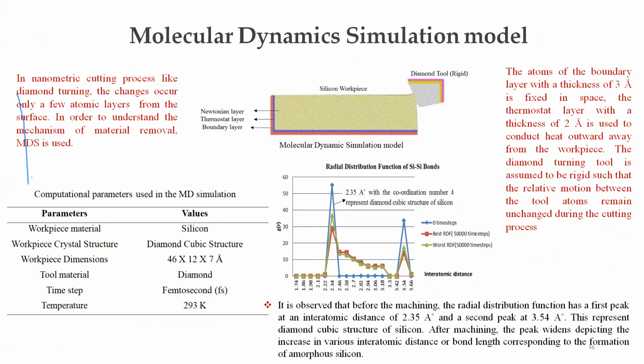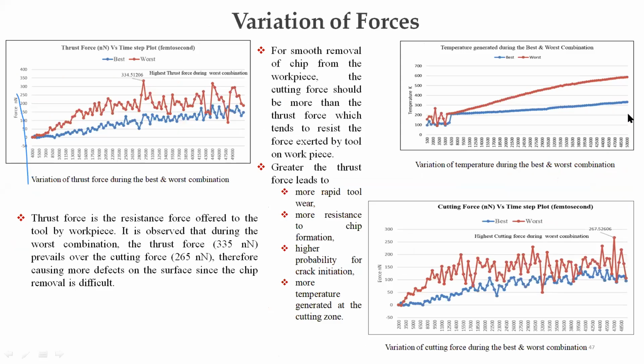Now, since I'm talking about nanometric cutting, the things are not usually visible to us. So in order to analyze the process, we are into molecular dynamics simulation modeling. We use this model to analyze the nanometric cutting, the changes occurring in the material only a few atomic levels from the surface, and also to understand the material removal mechanism. So this is the model which we developed for this kind of machining, and we could study what phase transformation is occurring, what cutting forces and thrust forces exist, and variation of temperature at different points through this simulation model.